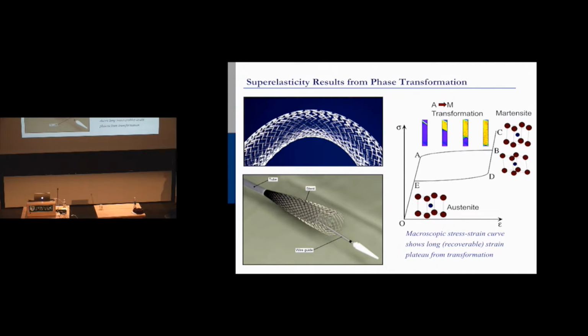And now when you release, you come back down and you start the reverse transformation from martensite back to austenite. This plateau, this is what gives you all that recoverable strain. So that phase transformation, that localized Lüders-like phase transformation, is what gives you all the recoverable strain that lets you squish these stents and these heart defect occluders. So you get it through this phase transformation.